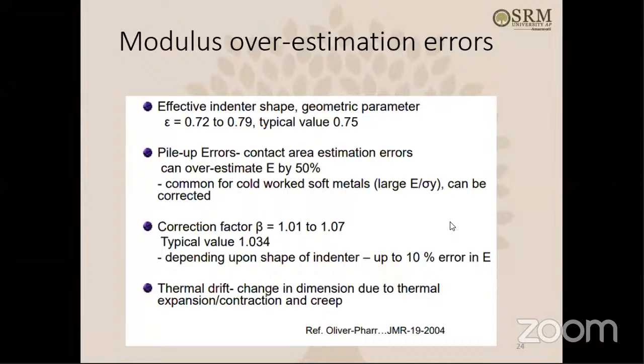So there were some errors that we found. Okay. So these errors are like, when you do the loading and unloading, and you test it and you get a loading and unloading plot, and then you try to estimate the modulus and hardness from those unloading curves. So we found that there are errors in their values. So if the modulus is coming as overestimation, okay, suppose modulus of the aluminum is supposed to be 70 and we are getting maybe 90, 100, 150, then what is the reason? So these are the errors that we found.